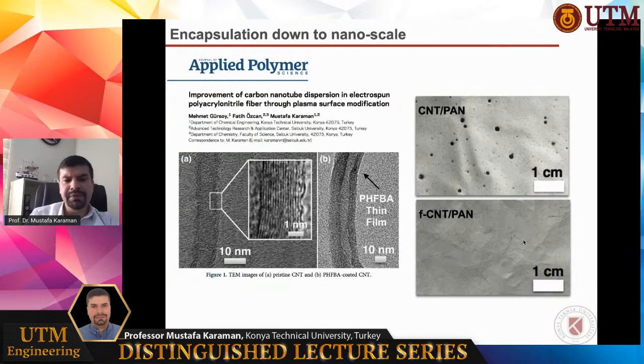So in this study, we improved the dispersion of carbon nanotubes in electrospun polyacrylonitrile fiber. We deposited a hydrophobic material using PECVD. Here you can see a carbon nanotube. Carbon nanotube is a nanomaterial itself. It has just a 10 nanometer diameter. And with the help of PECVD, we managed to have very thin polymer layers on the substrate surfaces.